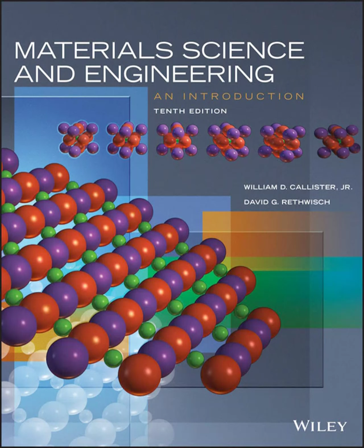Exactly. Real-world process times. And there's also a handy relationship, right? Something like x squared over Dt is constant. Yeah, that's useful. If you want to achieve the same concentration, CX, at the same depth, x, then the quantity x squared over Dt must be constant. This means if you change the temperature, which changes D, you can easily calculate the new time needed. Like comparing treatments. The example showed a 10-hour treatment at 600 degrees C for copper and aluminum is equivalent to over 110 hours at just 500 degrees C. That temperature difference really matters. It makes a huge difference.